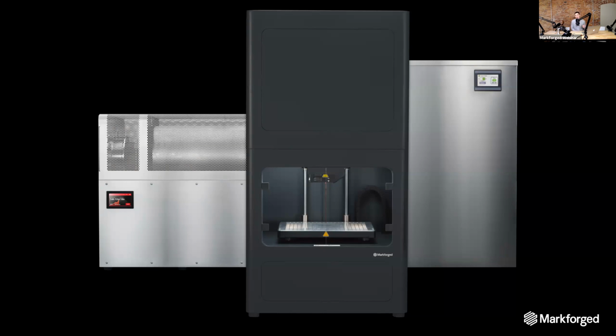When you look at metal injection molding, the technology that fathered this one, the parts that are primarily metal injection molded are very small. To allow us to print larger parts, like something of this size here, you need a slightly hollow infill that allows the debinding system to dissolve most of the wax and the sintering system to burn it away. In that sintering process, there's about a 17% shrink, but it's easily calculable, and we account for it in our own process. So that's a little bit about the Metal X.